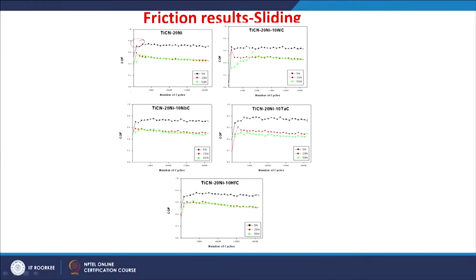This running-in period as well as the steady state is observed in all cermets, but there is a difference with respect to the load or the cermet compositions. Let us understand with respect to load. The coefficient of friction in the steady state is higher for any cermet at the lower load of 5 Newton, whereas 20 Newton and 50 Newton load conditions gave reduced friction compared to 5 Newton, but there is not much difference in the friction obtained at 50 or 20 Newton. But there is a difference in the steady state coefficient of friction value.